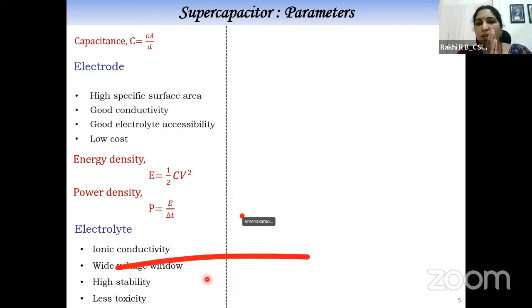Now, the energy density, half CV square: we know that C is a parameter which is associated with the electrode material or the electrode structure, whereas V is the property which is associated with the electrolyte. An excellent electrolyte should have good ionic conductivity, wide potential window, high stability, and less toxicity. For lab scale purposes, we usually use water-based electrolytes for the initial testing, but water-based aqueous electrolytes have a problem,